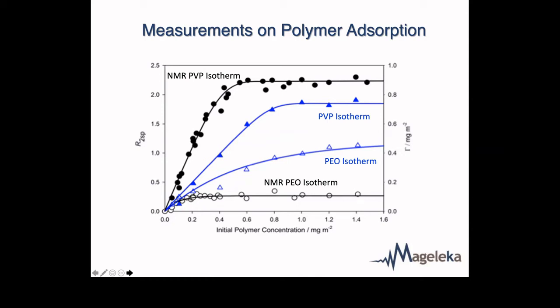Now, with the NMR experiment, all you do is you put your silica sample in the NMR tube, measure the relaxation time, you add 1 milligram of polymer, measure it again, 2 milligrams of polymer. So you can get one of these adsorption isotherms probably within half an hour once you know what you're doing. So this is terrific because you can now see, for example, PEO, PVP adsorption. The PVP is much more strongly adsorbed than PEO.